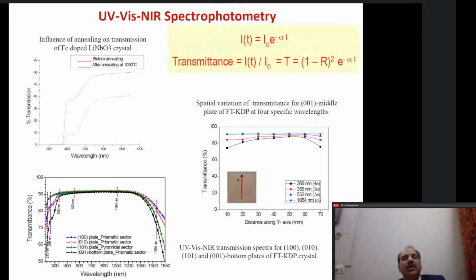One of the very conventional ways in which all crystal growers first test their grown crystal is UV-visible and IR spectroscopy, right? For example, in the case of lithium niobate, once we had doped it with iron, we tried to see what the transmission is. You will see it before annealing and after annealing. We were studying the influence of annealing on this iron-doped lithium niobate, and we were able to find that there is a drastic change in the transmission. Also, certain defects were getting annealed during the annealing process, and this was one of the interesting studies.